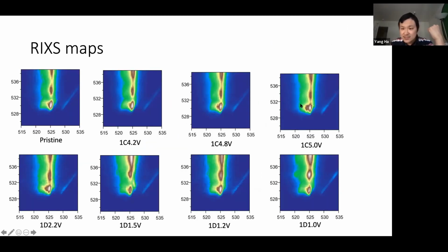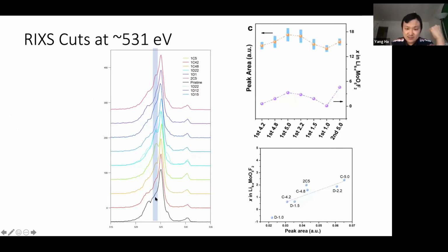To better analyze that, we can take a RIXS cut right at this 531 eV, and this is what we have. This shoulder corresponds to the oxidized oxygen feature. When we charge it, this peak gets more and more intense. And when we discharge, we lose this feature. And when we charge it in the second cycle, it shows up again. It has a very nice correlation with the capacity here. Even though it's not a perfect linear correlation, it's highly correlated.